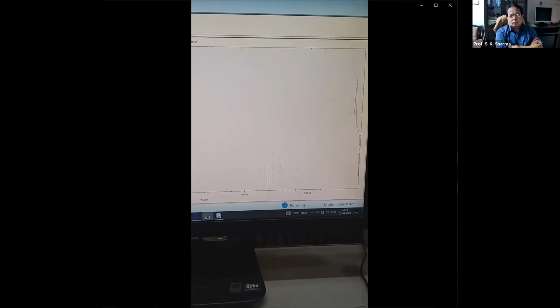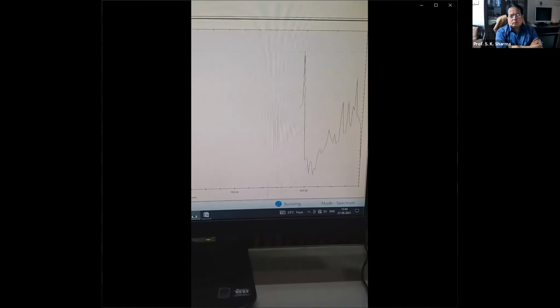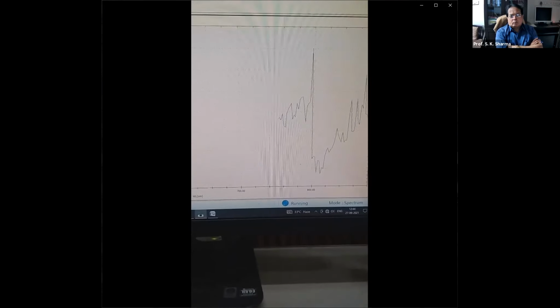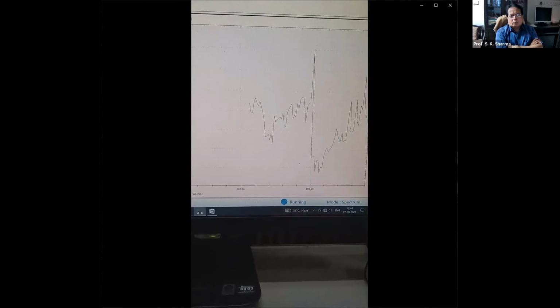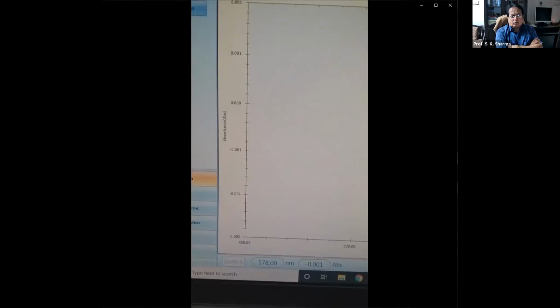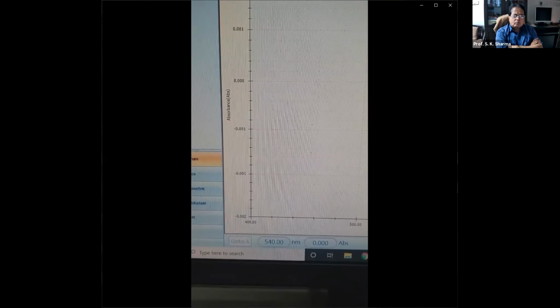So I run it. So now you can see that the recording has started, and you will find a spectrum being plotted on the screen. That spectrum you can see either on the spectrophotometer itself or on the computer screen. So on the computer screen you see that the scanning is taking place from right to left, because from the higher wavelength side it is scanning towards the lower wavelength side, and you see some spectrum is being plotted. But you look at the scale of the measurement, the absorption is of the order of 0.001. So it is a very low absorption.